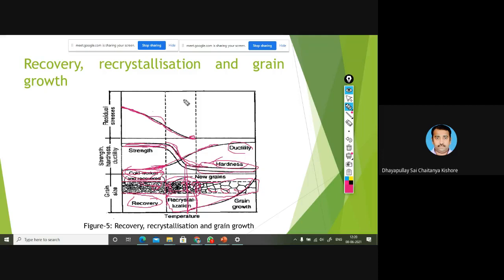Whenever the grain size increases, there will be no proper bonding between the side by side grains. Due to that, it will reduce the strength. There is a reduction in the hardness, but there is an improvement in the ductility. So these coarse grains are always the reason for low strength, low hardness and good ductility. If you want that, you prefer the increase in the grain size. So that is the explanation regarding recovery, recrystallization, and grain growth.